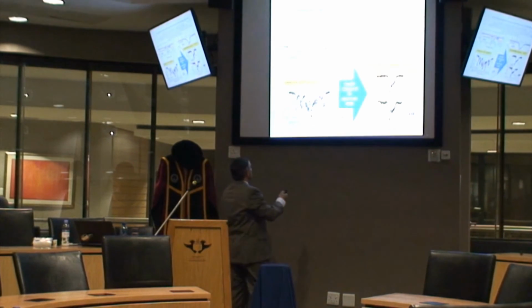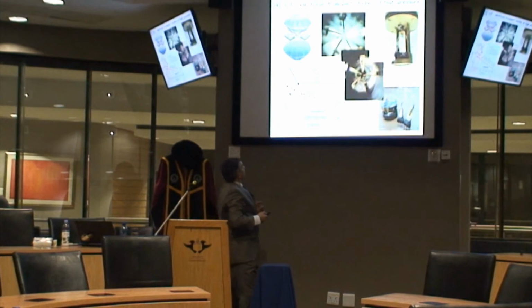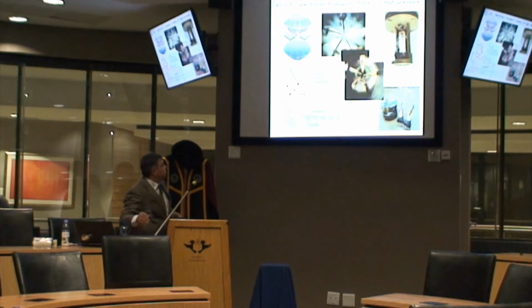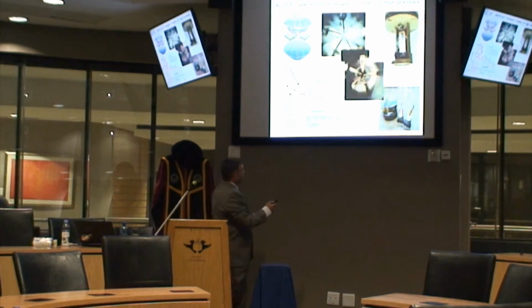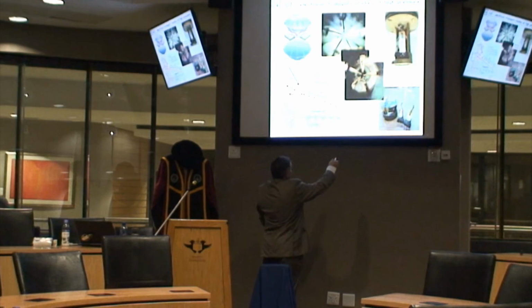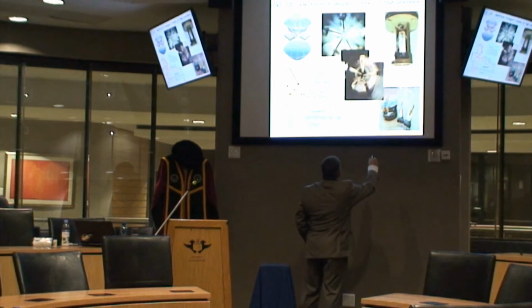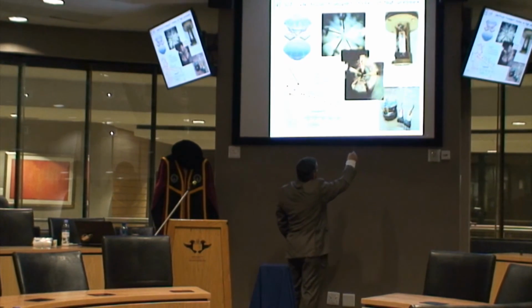For my physics colleagues, what's actually happening? Electron hopping from 2 plus to 3 plus and back. A dynamical process. And my last example, we can bring lead wires into the cavity, and we can measure the resistance of the material. And so here you see an iron-based material at 170,000 atmospheres. The sample insulated from the metallic gasket, inject current, measure voltage, and then compute the resistance.